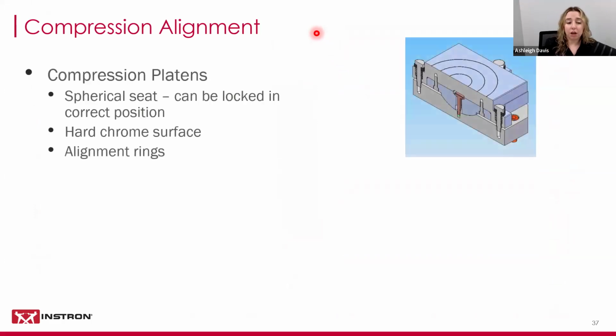Lastly, I want to talk about alignment and compression. For compression testing, we typically use compression platens, which have the option of a spherical seat. So one platen would need to be spherically seated, typically the upper one, and one would be fixed. You drive the platens together, and once they're perfectly parallel, you lock that spherical seat, and this essentially meets the NADCAP compression alignment requirements. They have hard chrome surfaces to prevent damage, as well as alignment rings to help you locate your fixtures when you're loading.